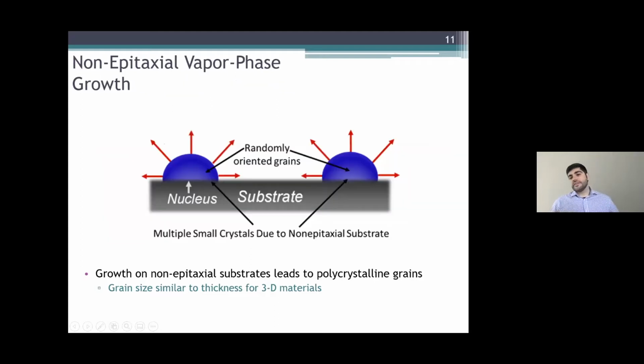The reason for this is simply that your precursors come in vapor phase and react on your surface. They nucleate your desired material, but since there's no epitaxial template, nothing controls the orientation of all of these nuclei relative to each other, and you don't have control over the geometry in which they're growing. So essentially they'll grow in the vertical direction and the lateral direction at within an order of magnitude of the same rate.